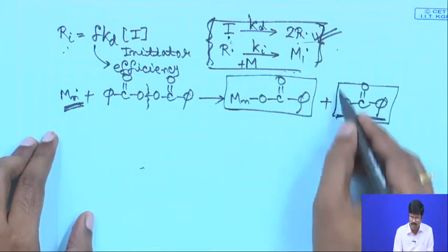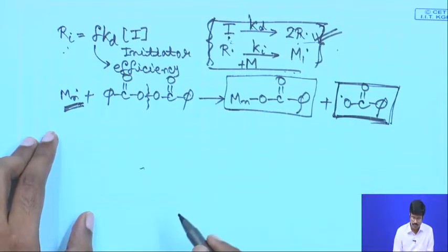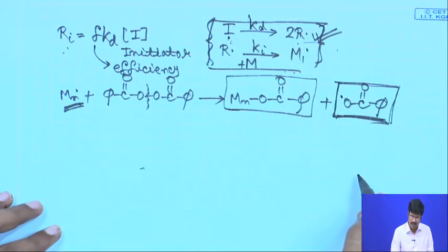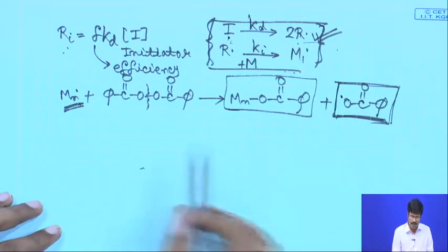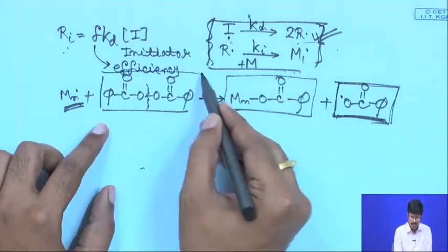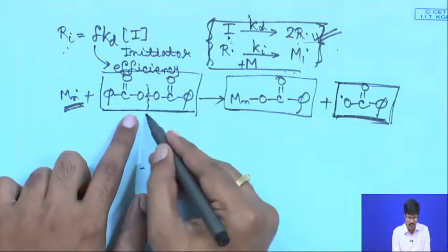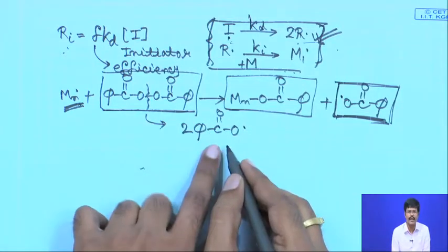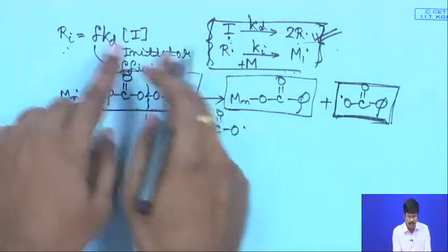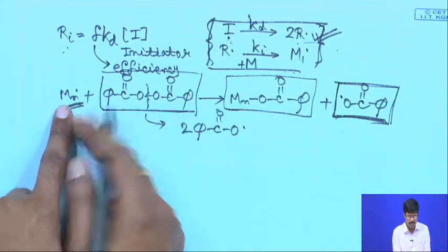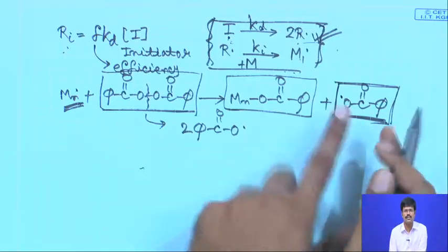Now, this benzoyl radical that is produced can of course initiate another polymer chain. But the problem is that one of these initiator molecules should create 2 radicals. If each of these radicals initiates one polymer chain, then the efficiency will be 1. But actually this molecule is terminating the growth of Mn dot, so in effect it is giving one radical, which is incorporated into a polymer chain.